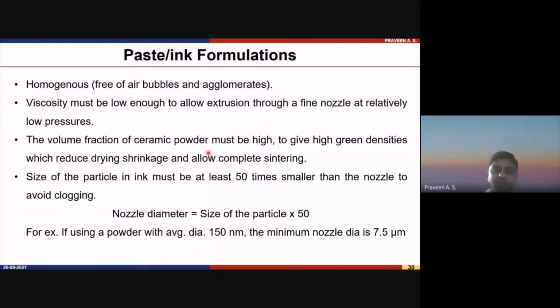Agglomeration means it's forming a chunk of material inside the barrel. So that will cause choking of flow. The nozzle will choke because of this agglomeration. And you should have a sufficient viscosity so that you don't need to apply very high pressure for the extrusion of the system. That depends on how much volume of solid material you are adding to that